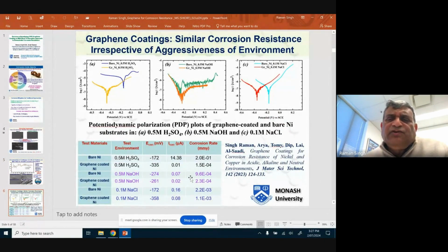Another thing that I wanted to quickly share with you is that if you have graphene coated nickel and you expose it to harsh corrosion tests in different types of environment, like sulfuric acid, alkaline environment, neutral environment, irrespective of the environment, the corrosion resistance is the same. Why I'm saying that is because the intercept of these two arms of this plot gives me corrosion resistance, this intercept, right? And that intercept value is the same irrespective of what environment I'm doing this test in.